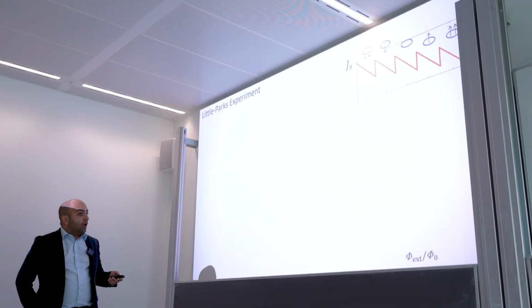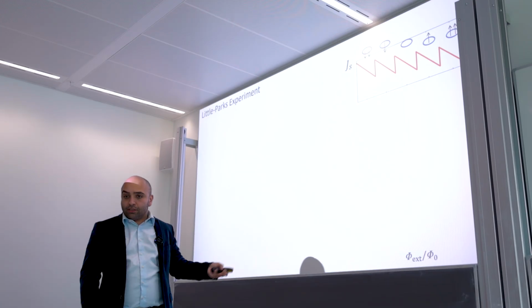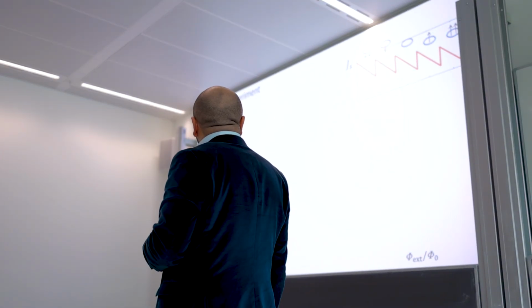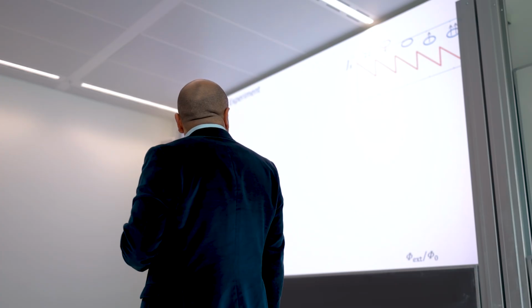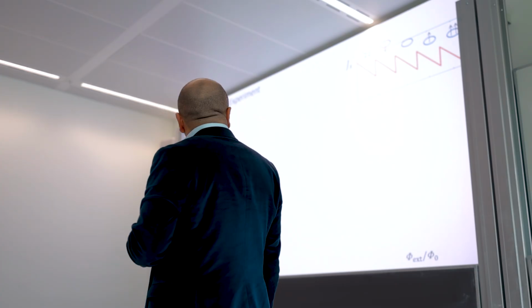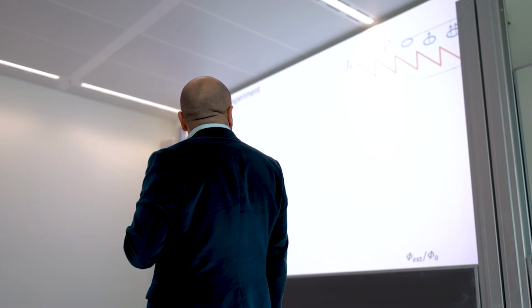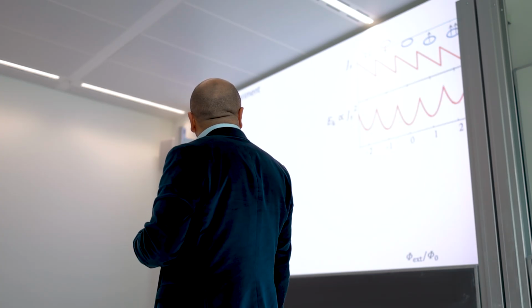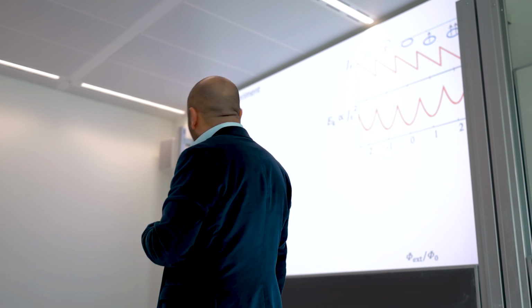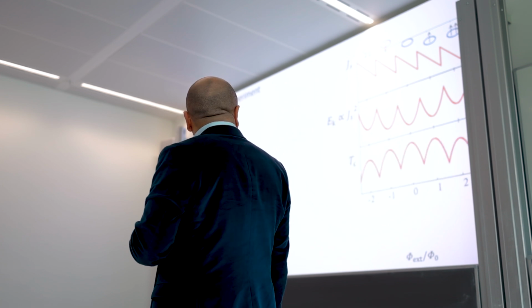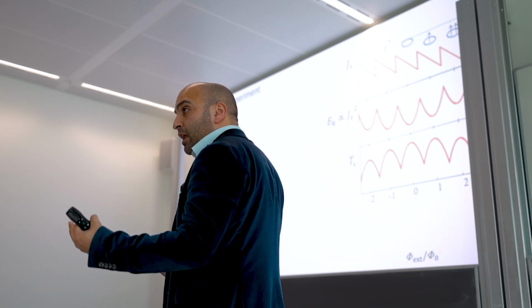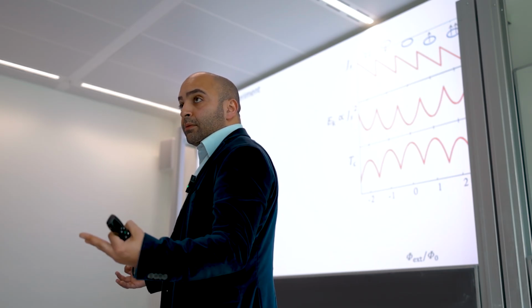Now, well, this actually is just another thought experiment. They measured this. It was a very important experiment. It's called the Little-Parks experiment. And how do you measure it? Well, basically, this current that we talked about, as I said, it has kinetic energy. So that's kinetic energy proportional to J squared. And this kinetic energy has to be taken away from the energy of your condensate. And what does that do to your transition temperature?